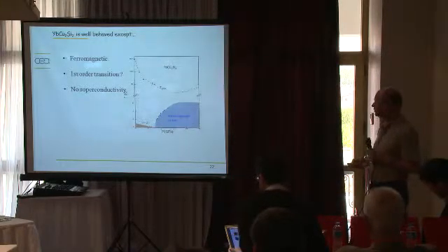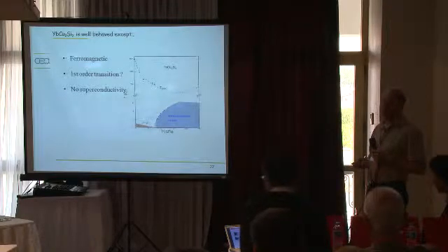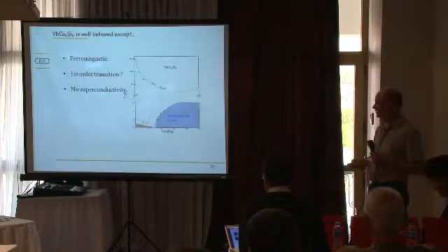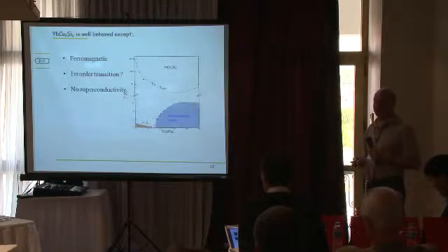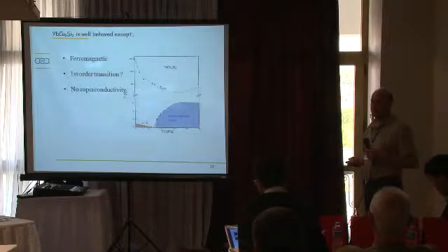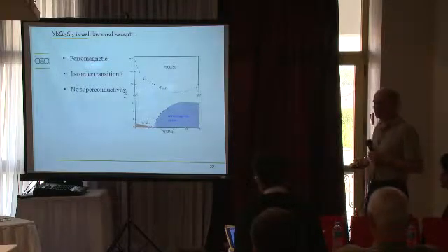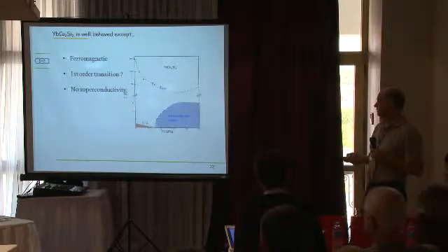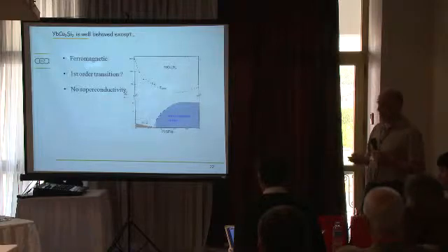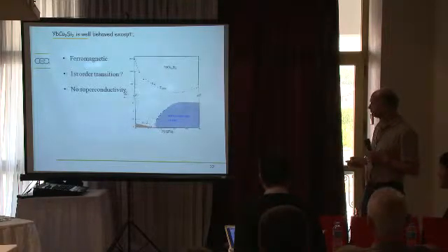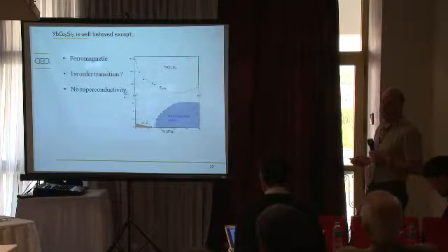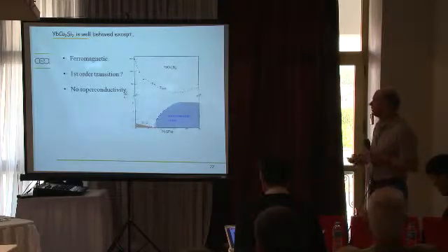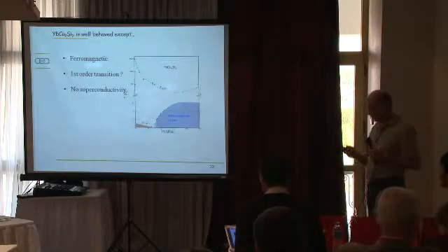We've also, of course, looked closely to see if we could find signs of superconductivity here. We didn't find any. In a cerium system with such pure crystals, superconductivity at a critical point seems to be the rule rather than the exception. In ytterbium, it's very rare because there's only one case possibly known. Of course, the two previous points, ferromagnetism and first order transition, could also be strongly against superconductivity.